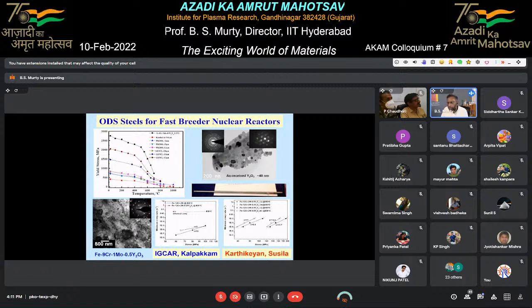And these are all now available, and such materials give you extremely high strength even at 700 degrees centigrade, whereas a normal steel such as 9 chrome 1 moly steel gives you strength only up to about 500 degrees centigrade, not beyond. So we can demonstrate that this is possible.